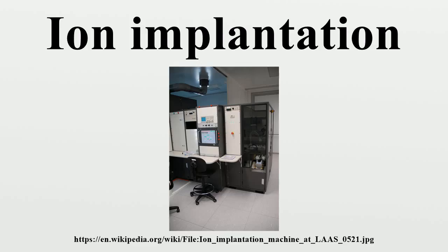One prominent method for preparing silicon-on-insulator substrates from conventional silicon substrates is the SIMOX process, wherein a buried high-dose oxygen implant is converted to silicon oxide by a high-temperature annealing process.